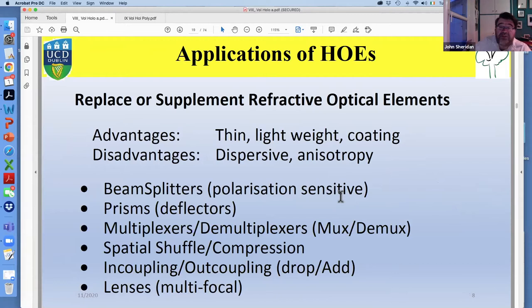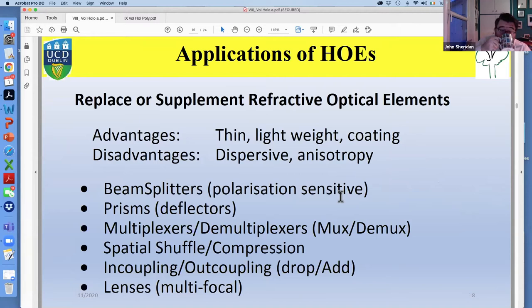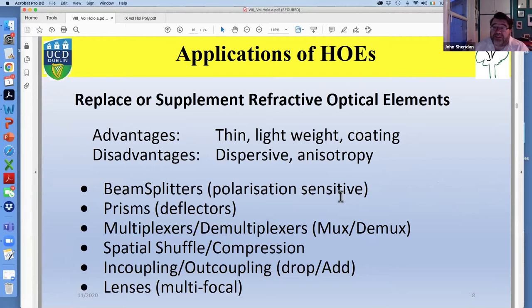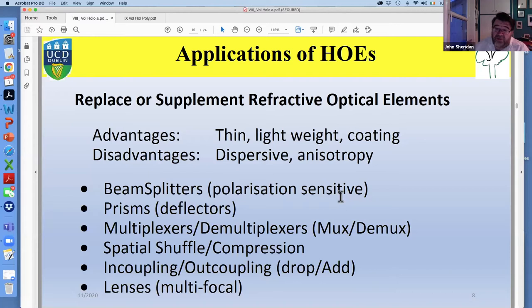I started talking about holographic optical elements and wanted to give some examples of their applications as motivation. Last day we got to discussing HOEs being seen as replacements for bulky refractive optical elements. They have significant advantages: compactness, being thin and lightweight, and you can coat materials with polymer layers. In the past layers were about 100 microns thick, but now commercial products with very high modulations can be made at 20–30 microns, and materials are now sensitive to multiple wavelengths — red, green, and blue.